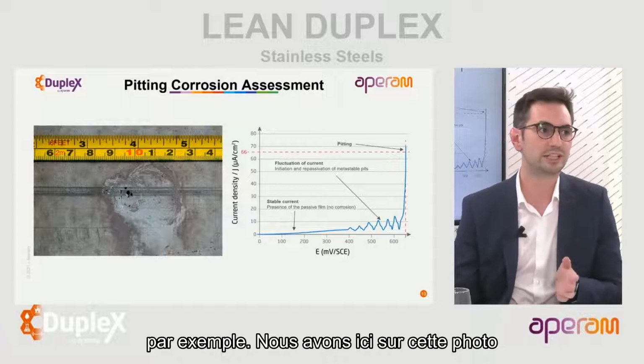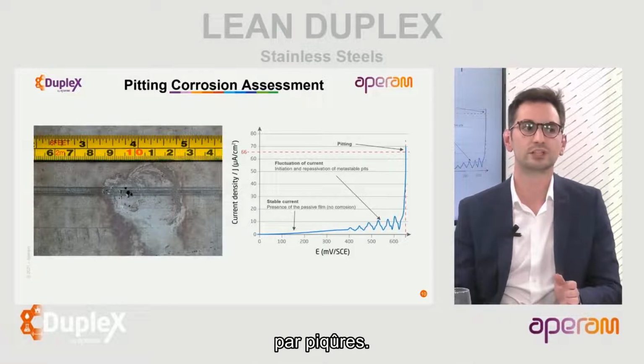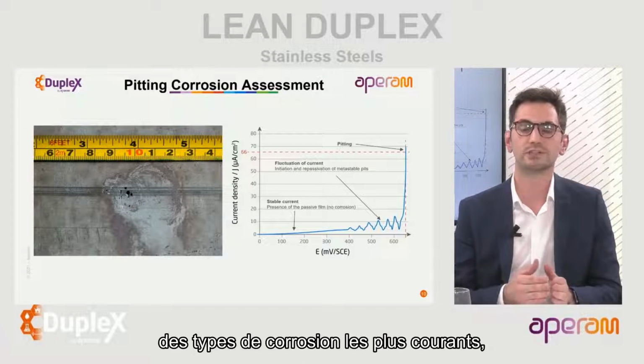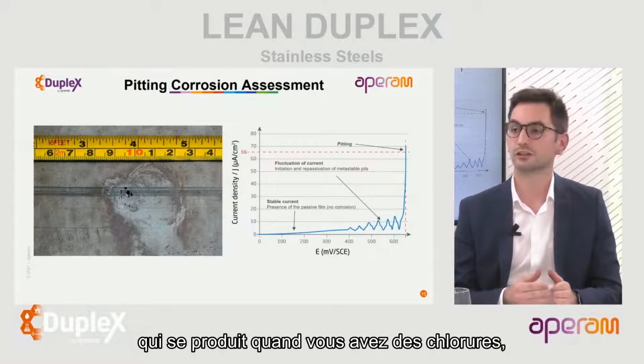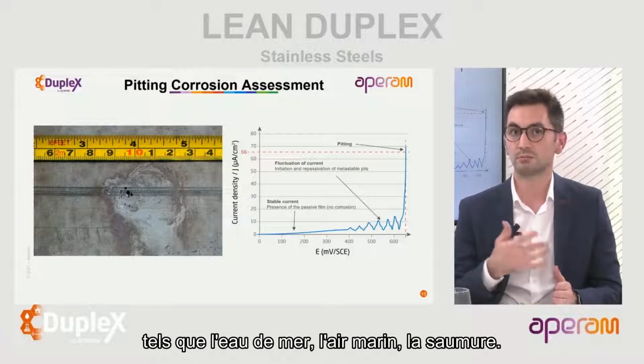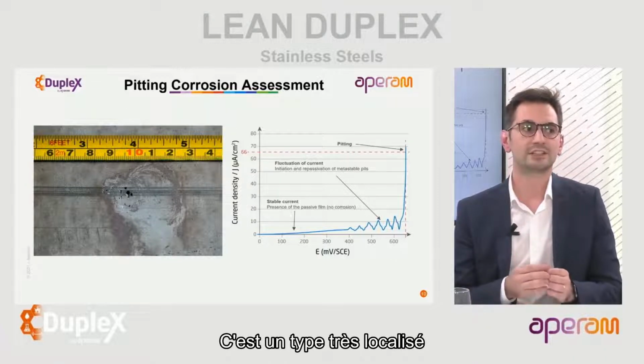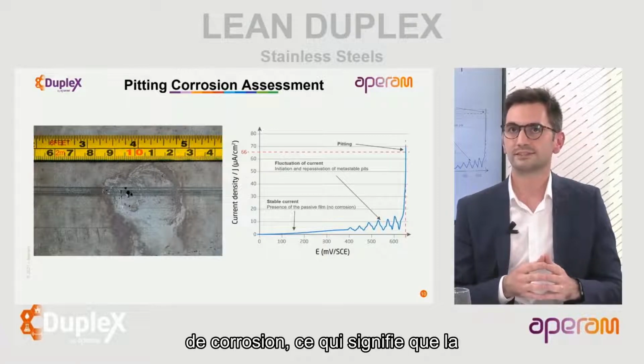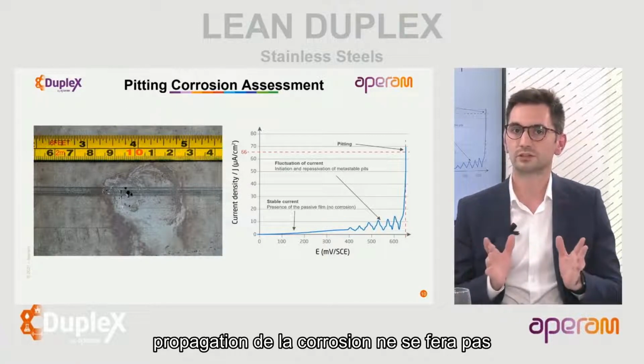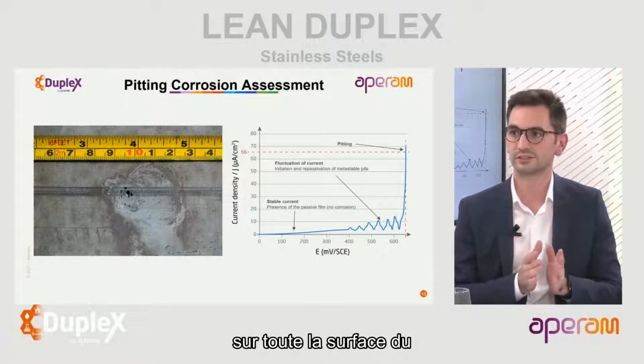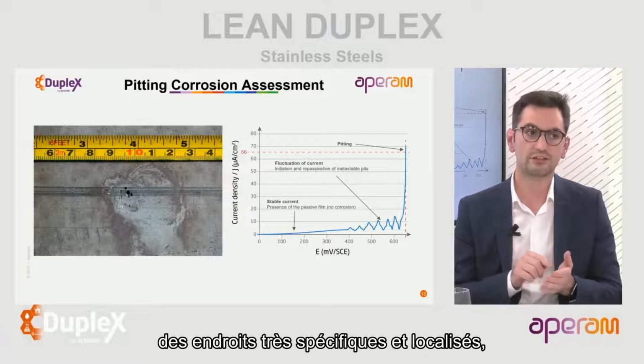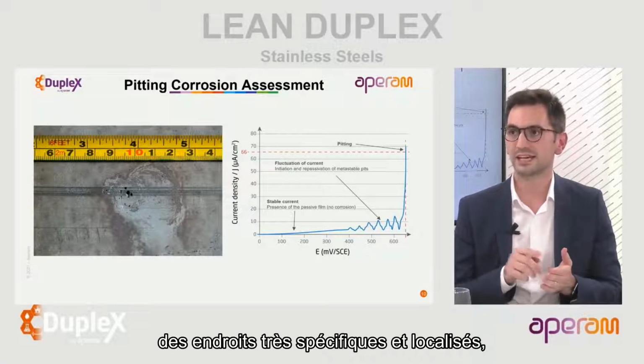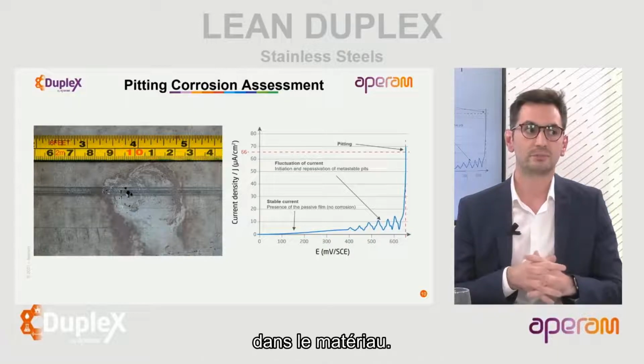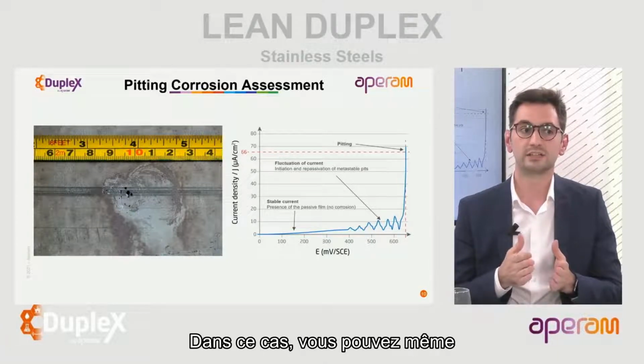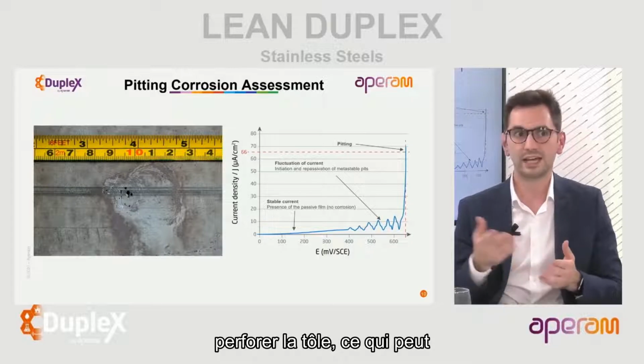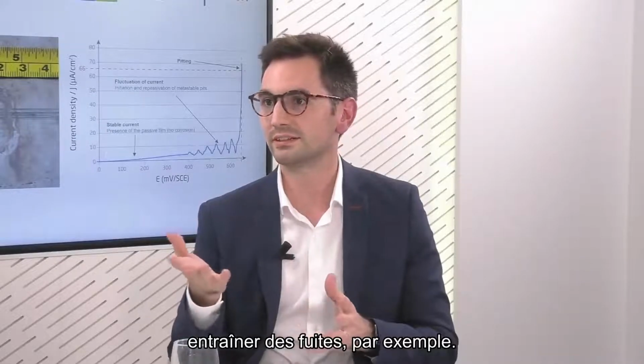We have here on this picture an example of what is called pitting corrosion. Pitting corrosion is one of the most common types of corrosion, and it happens when you have chlorides, which means seawater, marine air, brine. It is a very localized type of corrosion, which means that you will not have the propagation of the corrosion all over the surface of the material, but it will initiate on very specific and localized spots, and then it will propagate in the depth of the material. And when you have that, you can even perforate the sheet, and then it could lead to leakages, for example.